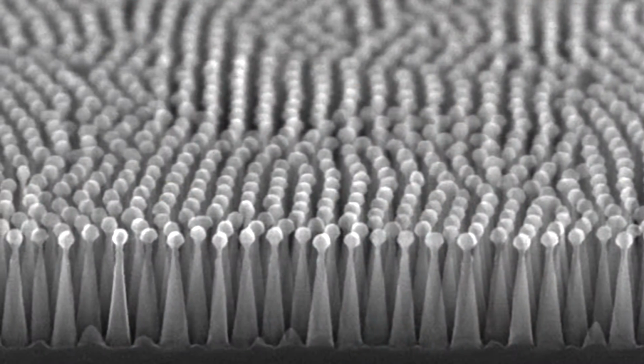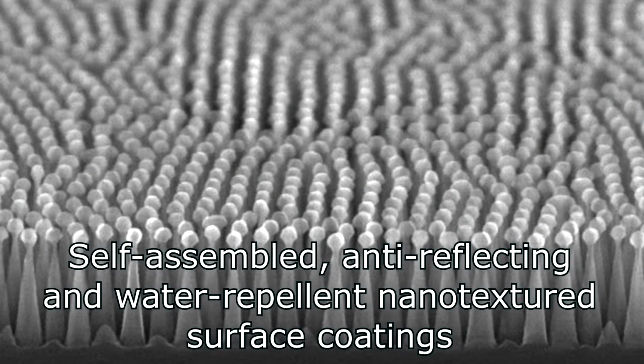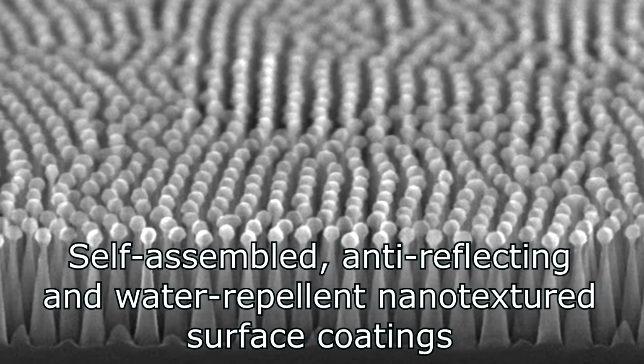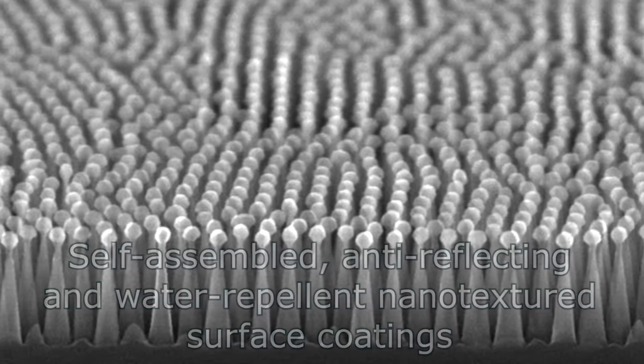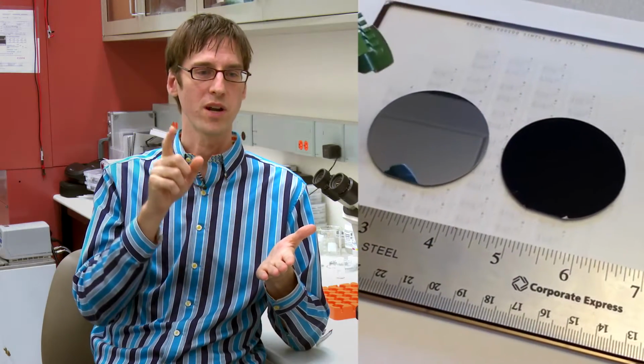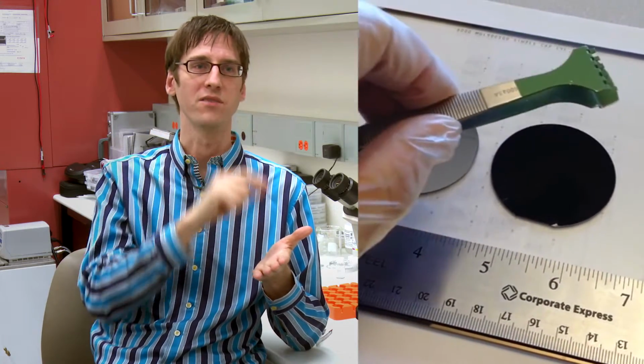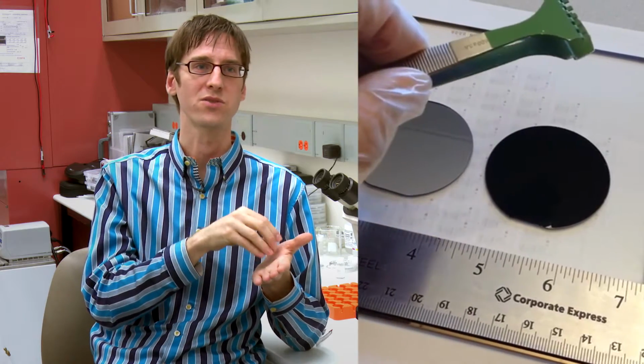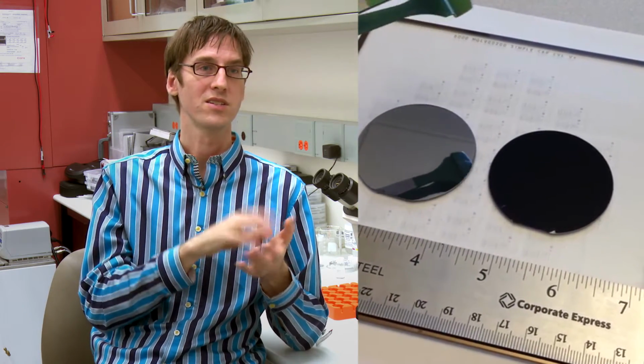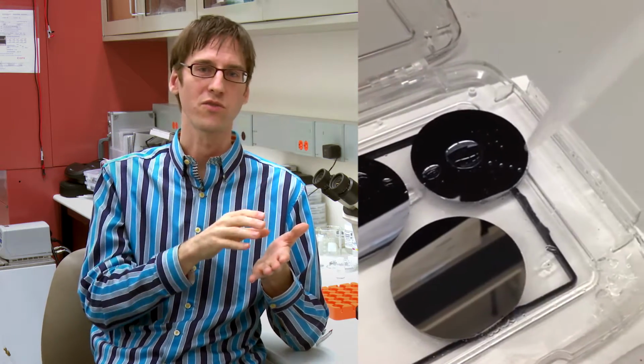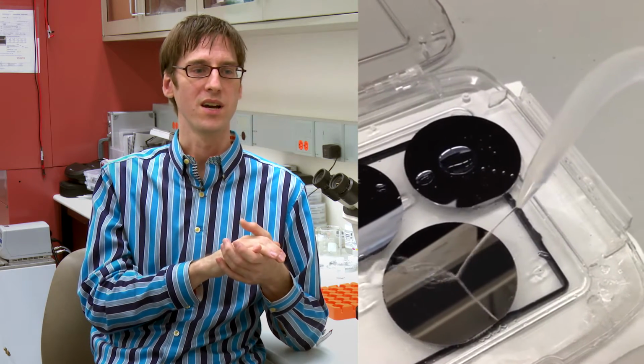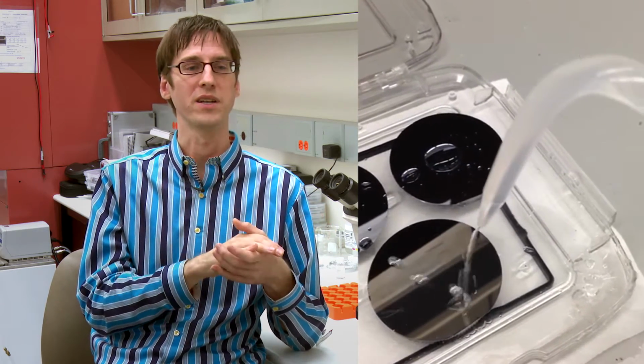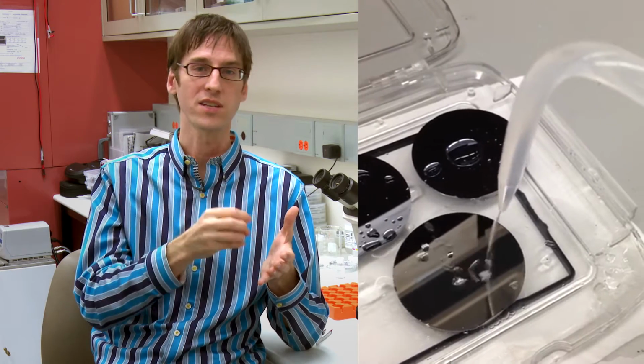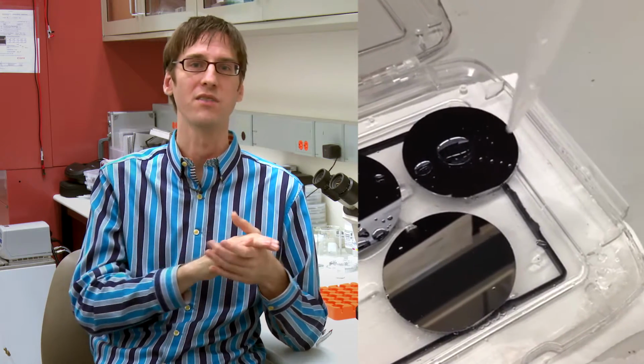To give a concrete example, we have the ability to nanotexture a surface to control both its optical properties and its wettability properties. So for a solar cell, we want to reduce the amount of light that's wasted in reflections and instead have that light couple into the solar cell and be absorbed. Simultaneously, we want to tune the surface so that its wettability properties are what's called superhydrophobic. And what that means is that water will not stick to the surface and instead will just roll right off. And that makes surfaces inherently self-cleaning.